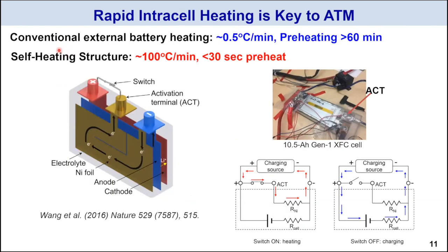And conventionally, heating is done externally, either by circulating warm fluid or by putting on an external heater, and those are all very slow processes, typically at a speed of 0.5 degree per minute, and going from room temperature to 60 degrees Celsius will take about an hour, okay? And this is why Tesla has this so-called on route battery warm-up strategy. In other words, if a driver needs to go get a fast charge, you have to tell the vehicle ahead of time, hopefully 45 to 60 minutes ahead of time, push the button, and then by the time you arrive there, the battery is warm enough to do a supercharge.